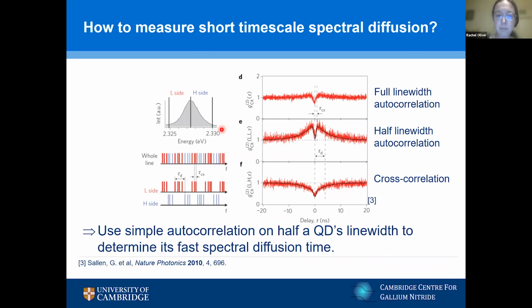Instead of doing their Hanbury Brown and Twiss experiment on the whole peak, they divided the peak into two halves, a low energy side and a high energy side. And we can imagine that the emission on the low energy side is about half the single photons, and the emission on the high energy side is the other half. And we get several emissions on the low energy side, and then a charging or decharging event occurs in the environment, and we switch to the high energy side, get a few emissions, and back to the low energy side. If we do our Hanbury Brown and Twiss experiment on just one side of the peak, we just see one of those sets of bunches of photons.